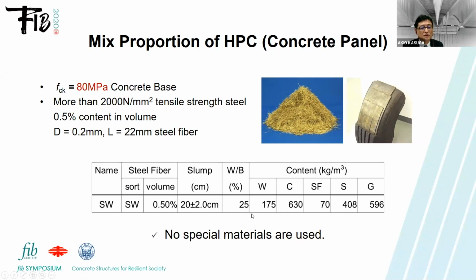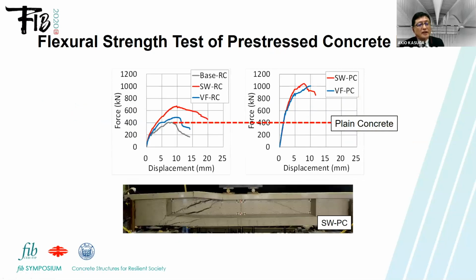And also this is mixed proportion. We use 630 kilograms of cement. And as you know, there is no special material. In order to get the strength of the structure, we use the fiber, as I said before, and also pretensioning, post-tensioning, and the beam. This is a base, 400 plain concrete, and after the putting in the steel wire, the strength is around 700. And also after the tensioning of the beam, the total strength of this structure is more than 1,000, compared with plain concrete, 2.5 times. So after that, we confirmed that this material can be used in the real structure.